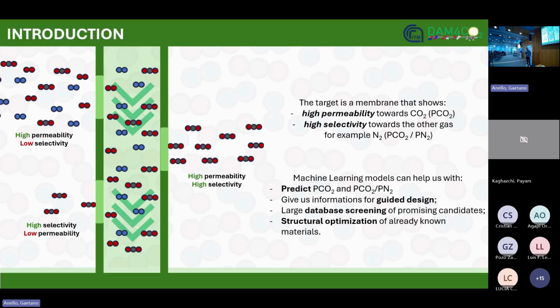So in this scenario, the best one is the one on the right with high permeability and high selectivity. So a lot of gas can pass through the membrane, and selectivity, so only the gas we want. And for a membrane, we can define two properties: permeability, which indicates the amount of the gas that can pass through it, and the selectivity, which is defined toward a couple of gases. So we do the ratio of the permeabilities. For example, we focus on nitrogen, and we can define the carbon dioxide/nitrogen selectivity.